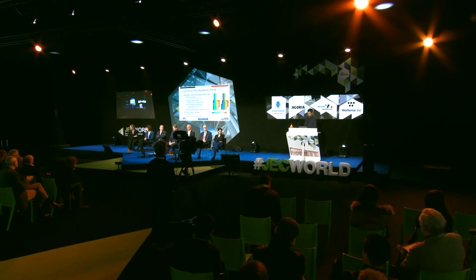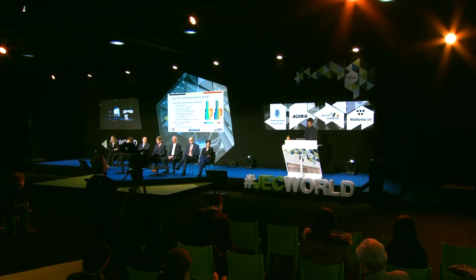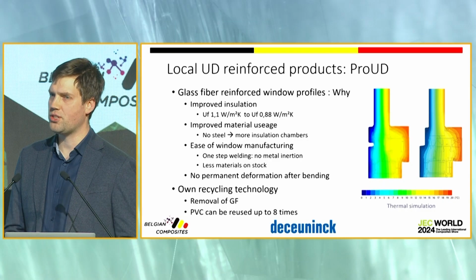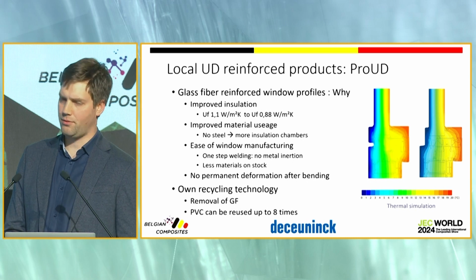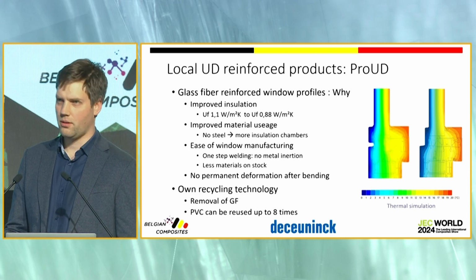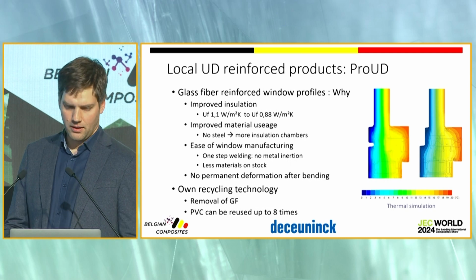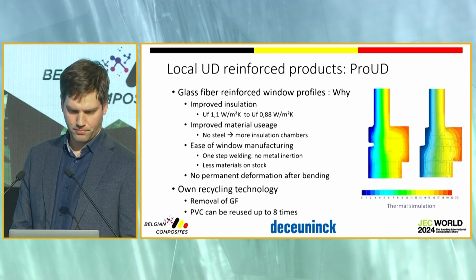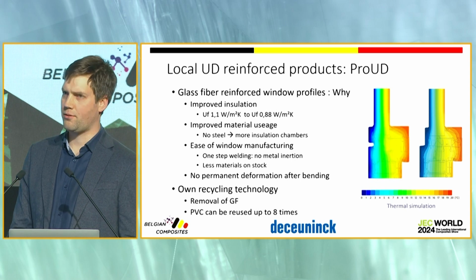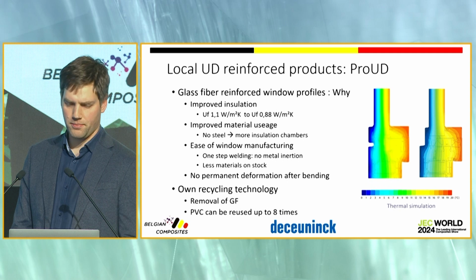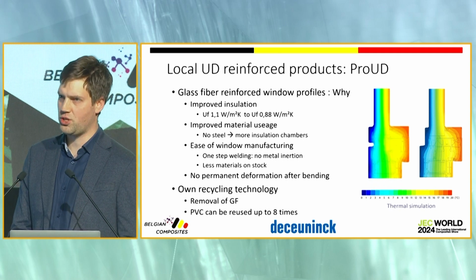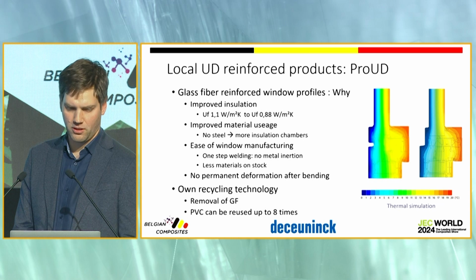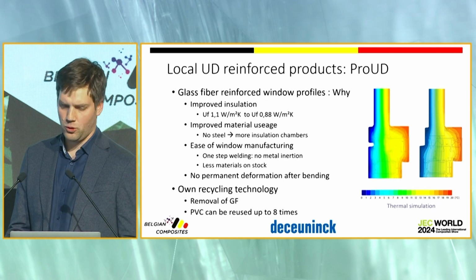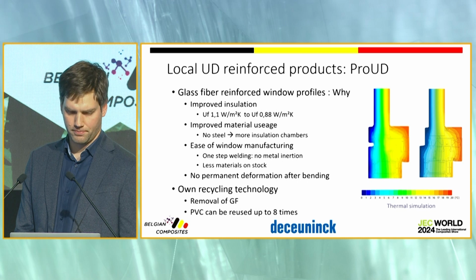So why would you use these glass fiber reinforced profiles? Well, the first thing is that you have a better thermal efficiency, because you do not have large chambers inside, as no steel is needed to have the stiffness of the window profile. So more internal chambers mean a better thermal insulation. On the other hand, you also have the window manufacturer, who does not have to keep a stock of steel profiles which he has to insert in the PVC profile. So this leads for him to a more efficient and simpler process.